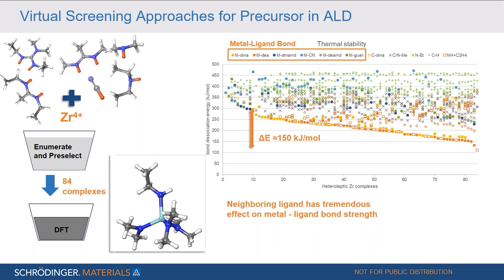And if we look at all the different complexes, what we can see here is that the same metal ligand bond strength varies strongly for the different complexes. So this means that the neighboring ligand has a tremendous and surprising effect on the metal ligand bond strength. And the good thing is we see that we get this valuable information already with a rather small virtual screening study.